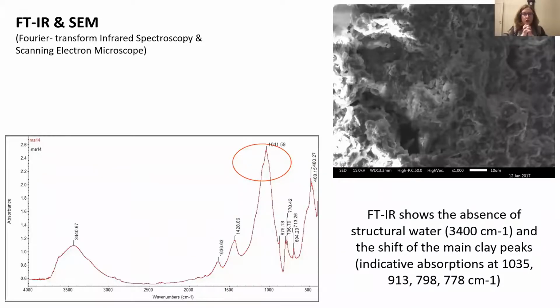Then we performed FTIR and SEM, and this was more to try to understand better the taphonomic bias that is affecting mudbrick manufacturing. As Maud mentioned before, even though mudbricks are mentioned in most of the excavator diaries, we do find little when we are actually conducting the excavation. And this is partly due to climate condition and taphonomic bias, but it's also because the only materials that are preserved are the mudbricks that have undergone a conflagration event.